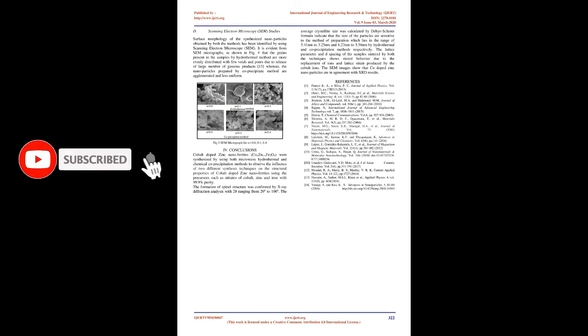Scanning electron microscopy, SEM. The surface morphology of the synthesized nanoparticles obtained by both methods has been identified by using a scanning electron microscope, SEM. It is evident from SEM micrographs, as shown in Fig 4, that the grains present in the samples by the hydrothermal method are more evenly distributed with few voids and pores due to release of a large number of gaseous products [13], whereas the nanoparticles prepared by the co-precipitate method are agglomerated and less uniform. Fig 4. SEM micrograph for x equals 0.0, 0.1, 0.4.